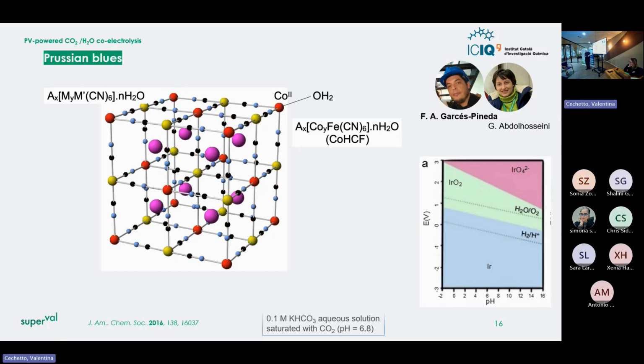The idea is that the oxides are unstable at low pH because the proton is attacking the oxo bridges and breaking the metals. Here, there's no oxo bridges. This material with cyanide bridges, again, is perfectly stable down to pH 0. But is it a catalyst?